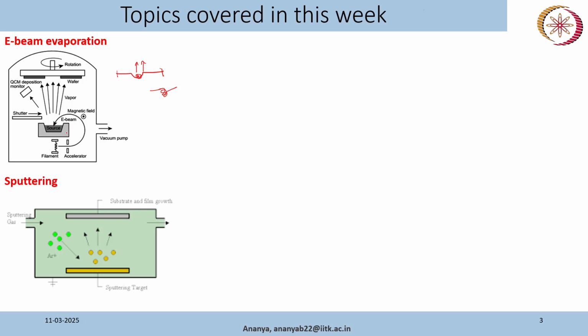We don't want to heat our crucible, we mainly want to melt our source, and then this beam scans a little bit. So if I can give you a top view of this, say this is your material and this is the crucible, this is your target material. The electron beam will move in this kind of direction, so that it does not hit the same spot. Also it does not heat the crucible, it only heats the target material that you want to evaporate. Now because of this high energy electron beam, this material, even if it has a high melting point, will melt and then it will evaporate and then deposit at the substrate that we keep at the top.